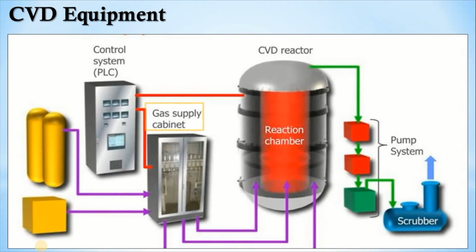The design of the CVD reactor depends on whether the starting material is solid, liquid or gas. The sublimation of a solid precursor depends on the surface area of the solid and contact time. Liquid sources often use a bubbler to vaporize the reactants, and a carrier gas, reactive such as H2 or inert such as argon, to transport the vaporized reactants into the reactor. Next equipment is a CVD reactor.